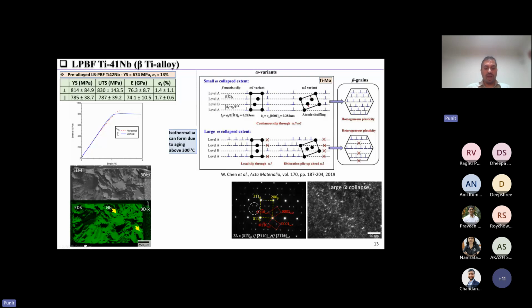And in our material, what happened was that we were looking to do fracture toughness tests, so we went ahead and printed these huge blocks, and printing one block was taking almost a couple of days. When you are printing such large blocks, the temperature of the printed material goes very high, and essentially we were aging our blocks for a long time. And if you age this kind of composition above 300 degrees C, you form this isothermal omega, which can have such an effect where you have heterogeneous plasticity.